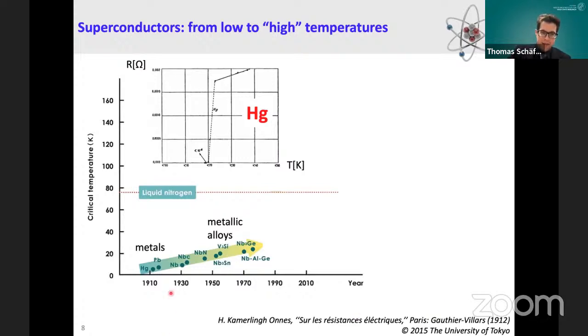But you see, this was a period of nearly 60 years, and not so much happened in the increase. If you would project this critical temperature line to the year when it crosses room temperature, I think we would be in the year 2300 or so. However, one came up with empirical rules of how to find new superconducting materials with even higher critical temperatures. And they are summarized in an experimentalist viewpoint, namely the so-called Bernd Matthias rules.